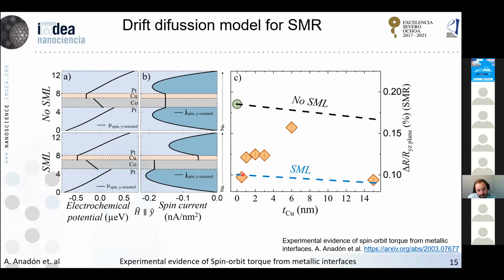Then for larger thicknesses, we observe some dependence of the spin-Hall magnetoresistance on the thickness of copper, and this dependence is most likely due to the dependence of the spin current generation at the interface of those three phenomena that I explained before. But it's very challenging to separate all these contributions, since all of the phenomena have a very strong dependence on the thickness of copper.